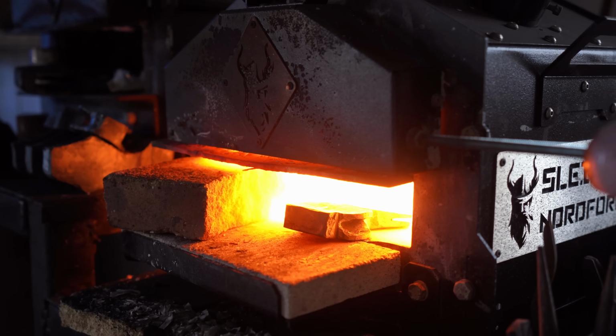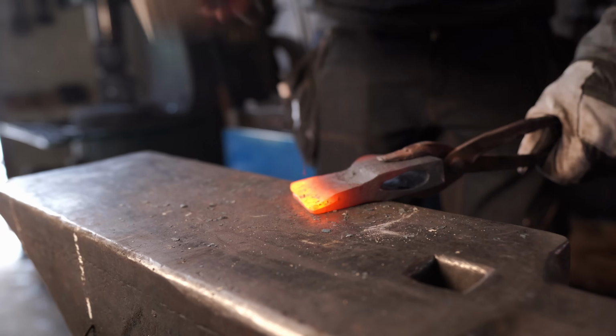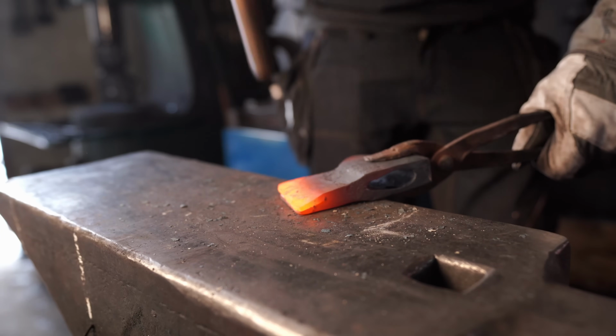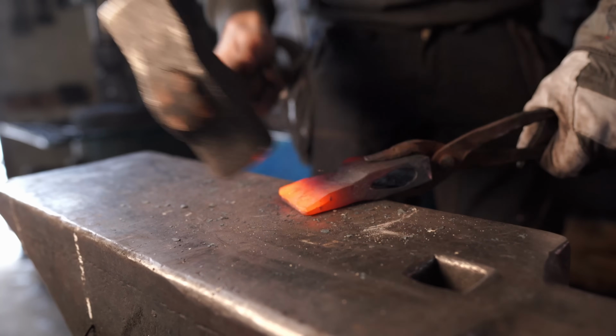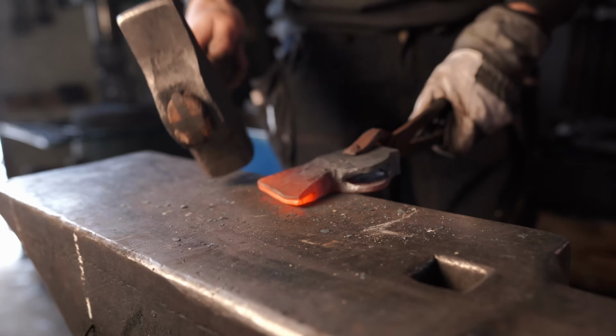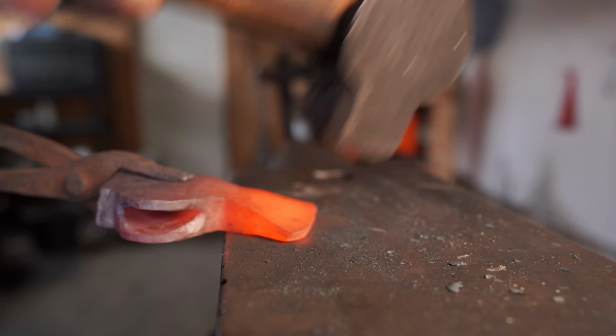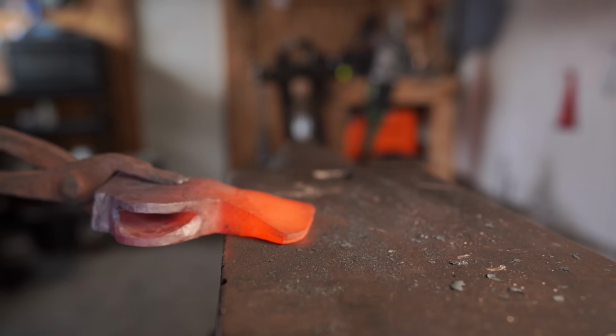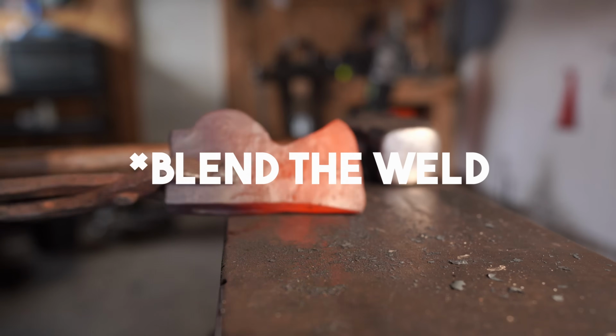Once the slot is cut, I heat it up again and hammer it shut. Whoops! What that does is slightly draw out the walls of the slot, tapering them and thinning them just a bit. That helps with the fit, makes the forge weld a little bit easier, and gives a much smoother transition from the body to the blade.